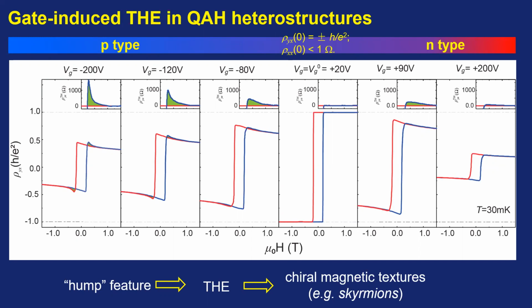This hump feature is usually called the topological Hall effect. It corresponds to the chiral spin texture in the real material. When you further increase this minus gate voltage, this hump feature becomes pronounced. If you apply a positive gate voltage, there is also a hump feature that comes out. If you further increase the positive gate voltage, this hump feature will disappear. In this state, the quantum anomalous Hall state corresponds to the Berry curvature in momentum space. When you inject some electrons in the sample, it shows this kind of topological Hall effect. It corresponds to the Berry curvature in real space.